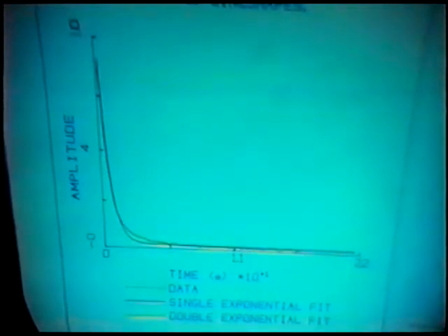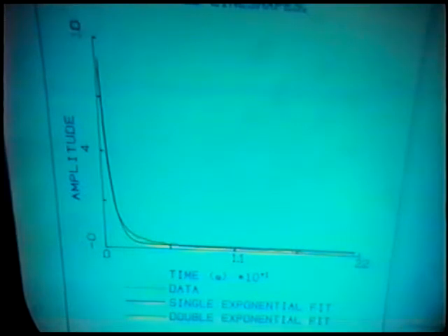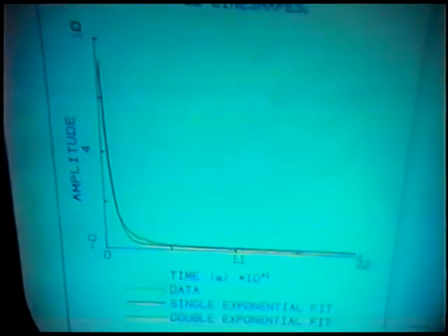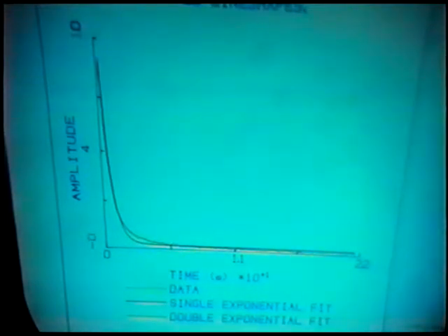Now, all these time constants are coverage dependent. This means that the situation is nowhere near as simple as the one we see here. So there's exchange between environments inside the material, and there's exchange with the surface and the gas going in one zeolite, coming out of the other. There's a whole lot of exchange processes which are behind these experiments. And we have managed to make a stab at what they're like.